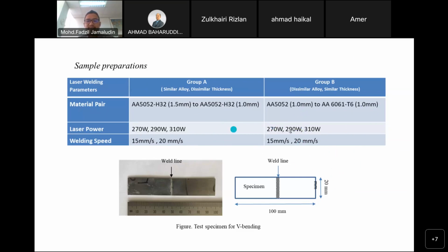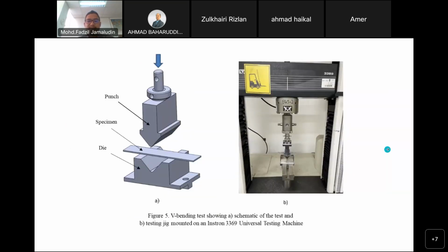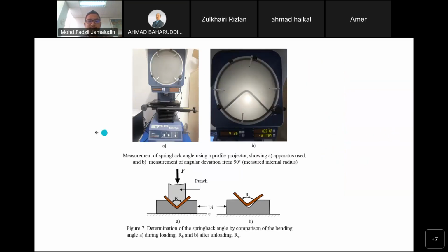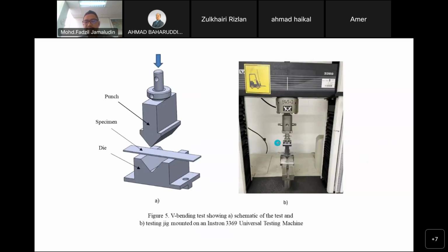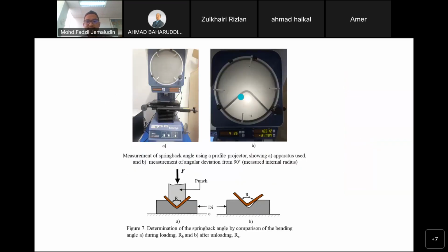And then these are the welding speeds that we use, the same parameters that we use. Then we designed this V-bending testing jig, which is mounted on the Instron machine. What we did is move the punch so that the coupon will bend by the punch, and it is kept. You punch it until it reaches the bottom, and then it is released, and the specimen will tend to spring back. The angle is 90 degrees, so the difference in the angle indicates the spring back angle after unloading.